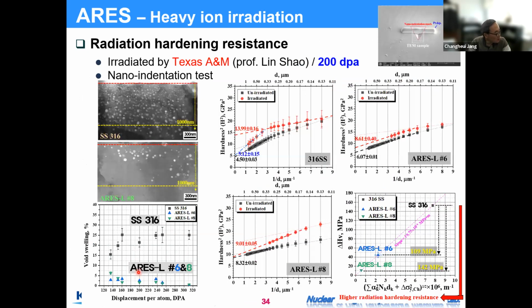But in the advanced nuclear power plant, the amount of neutron irradiation is much, much greater than 8 dpa. We are expecting somewhere around 200 dpa at the highest point. So we irradiated the material at 200 dpa, in this case at Texas A&M. And this one is again a comparison of the conventional alloys, and this is our developed alloy. And this is the measured volume increase. Compared to 316, which has around 25% volume increase, we have less than 5% volume increase. So there is a huge difference in terms of the volume change.